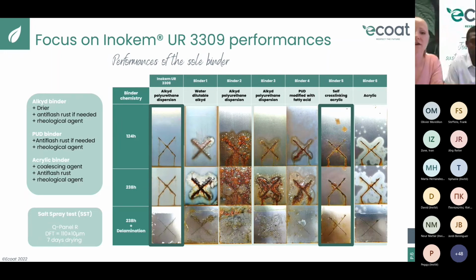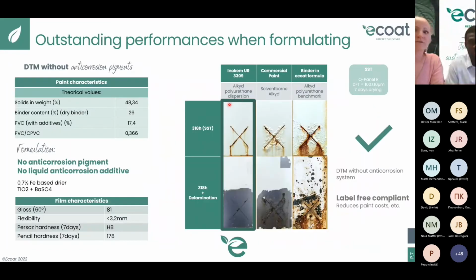Those results seem to be a good sign for paint performance, because we know that the binder gives the main properties to the paint. But we also know that formulation is very important in metal coating. So let's see if 3309 performs in formulation. We formulated the 3309 in a white paint. The formula is very simple because there is no anti-corrosion pigment and no liquid anti-corrosion additive. We exposed this paint in salt spray against a commercial solvent-borne alkyd and against a binder from the coating market, which was formulated in the same way as Inokem UR 3309.